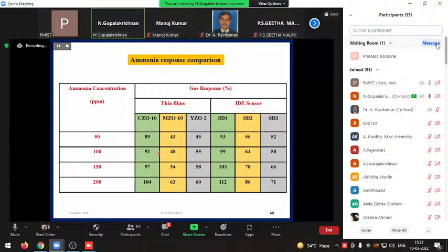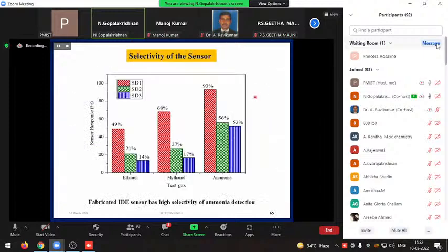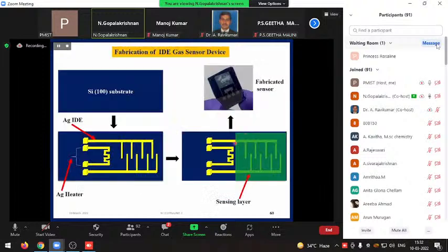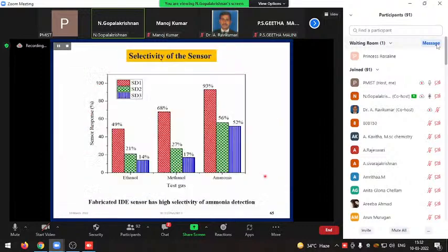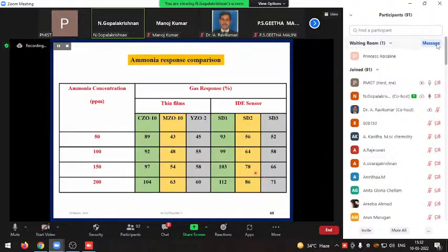So finally, this is the thing I want to talk about. This is a gas response comparison of thin film and IDE sensor. This is the first case, whatever I showed here. If we simply make the film by RF magnetron sputtering on a silicon substrate, then we measure the gas efficiency. Then second is the IDE sensor. So we compare both the thin film sensor and IDE sensor, and we can see it very well here. This is cadmium, this is magnesium, this is yttrium film here.